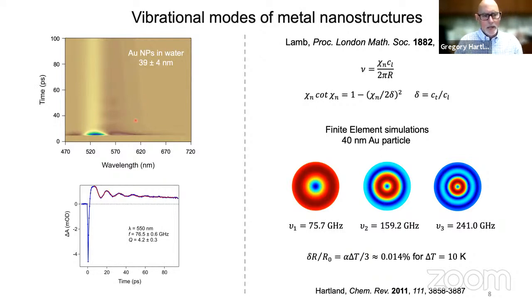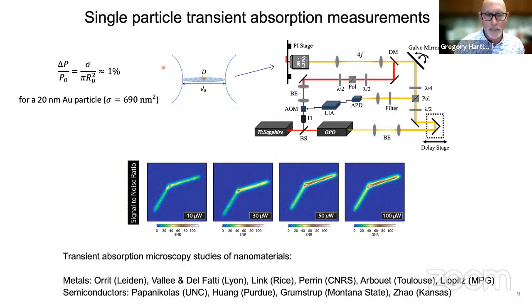And I think it's pretty obvious that this sample, which is actually not a very good one, has a size distribution of about 10%. That's not all that great. You can't get lifetime information. The damping is dominated by the size distribution. If you have very, very well-made samples of very narrow size distributions, you might be able to measure a lifetime. But the other way of doing it, of course, is just to look at a single particle. Okay, and so that's what we set out to do, and this is sort of how we do that experiment.